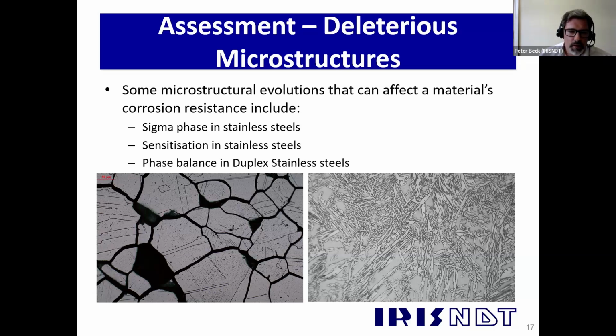In super duplex steels, we typically look for things like sigma phase. It can be an issue with austenitics, but more so with duplex steels. So we can replicate for that and look for that. And we can also look at the phase balance between the austenite and the ferrite in super duplex steels as well. So that's what this image is on the right, sorry, is a super duplex stainless steel.